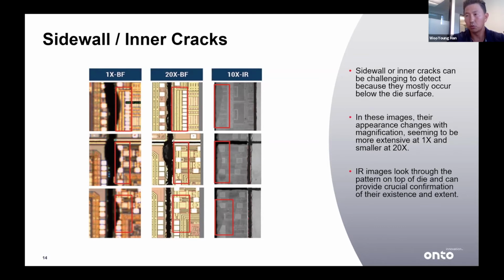So we have a tool with various magnifications that we can use for the inspections and find these types of cracks that are showing up underneath the surface. And on the right side, we also have an IR camera on the same imaging system, and when we look at it, this confirms the presence of the cracks underneath the die surface. Okay.